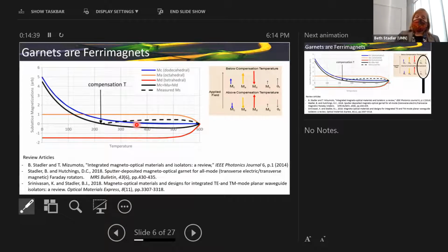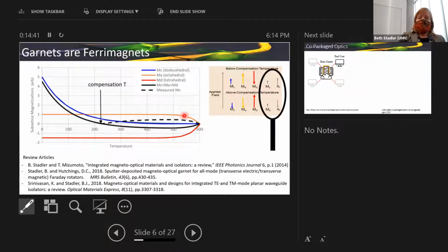The interesting thing is below the compensation temperature, if your moment is facing in one direction, your Faraday rotation is positive along that same direction. But when you get above that compensation temperature, even though your moment realigns and it looks like it's in the same direction, you'll have the opposite sign to your Faraday rotation.